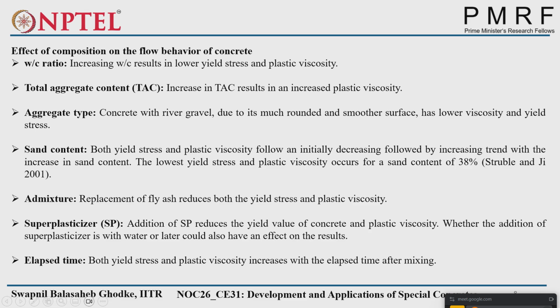Admixture. Fly ash reduces both yield stress and plastic viscosity. We saw this several times, because fly ash is spherical in nature. So that will be responsible for increasing the lubrication and increasing the flow. That's why it reduces the yield stress and plastic viscosity. Superplasticizer, elapsed time. Elapsed time, because we are keeping the same material.